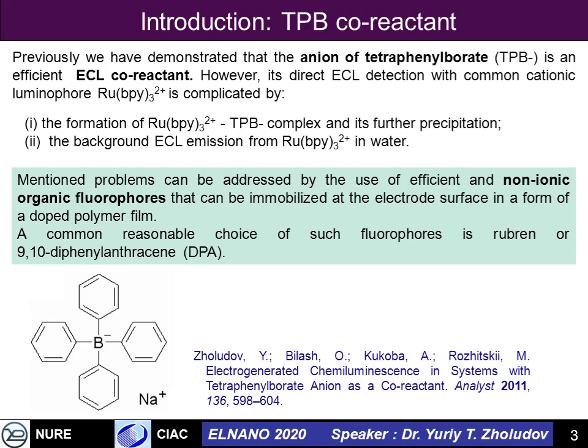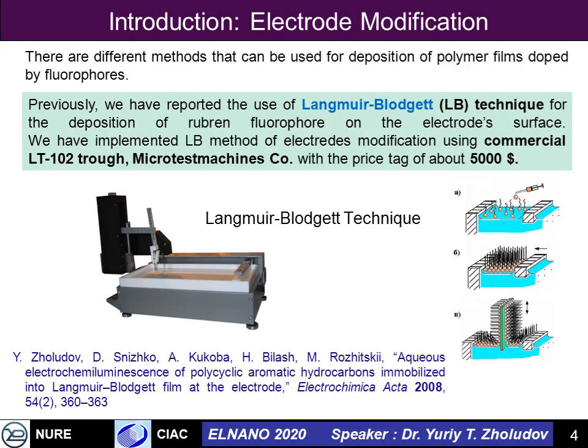In order to apply such a new coreactant as TPB, tetraphenyl borate, it is possible to use a different approach, where a fluorophore which is non-ionic and not water soluble is incorporated into a polymer film on the electrode surface. For example, previously we demonstrated the use of the Langmuir-Blodgett technique for deposition of ordered monomolecular films on the electrode surface, with the incorporation of some fluorophores, and ECL from such systems.